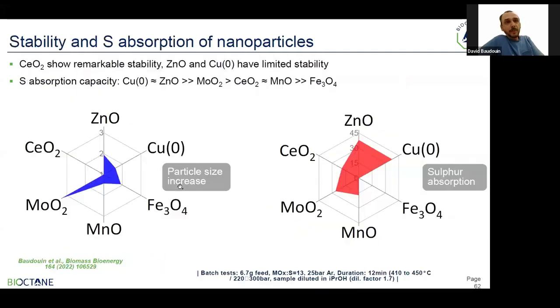Next slide, please. Zinc oxide showed also some good performance. Here are represented both the sulfur absorption capacity and some information regarding the physical stability under the conditions applied. While copper oxide has a good absorption capacity and desulfurization capacity, zinc oxide also has good ones, but their stability is limited. Cerium oxide, on the other hand, showed very good, excellent stability, and reasonably good sulfur absorption. So there are pros and cons in all cases, but that led us to identify cerium oxide as a good potential material for further development.